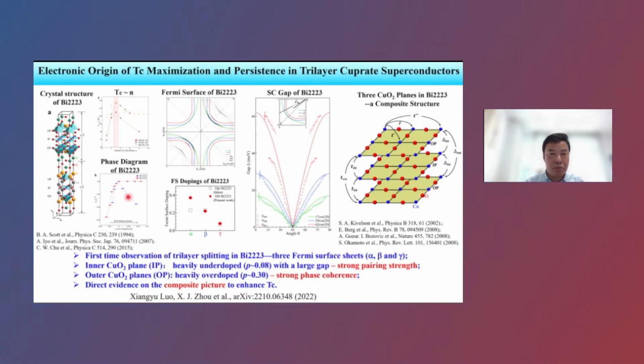Then it goes down with further increase of n. Also, Bi2223, the three-layer cuprate, has a different phase diagram. Usually, the usual phase diagram is that with increased doping, Tc goes up to a maximum and then goes down. But in Bi2223, the three-layer cuprate, Tc goes up, reaches the maximum at optimal doping, then stays constant with further increase into the overdoped region. And I think by using ARPES, we have for the first time detected the three Fermi surface sheets and